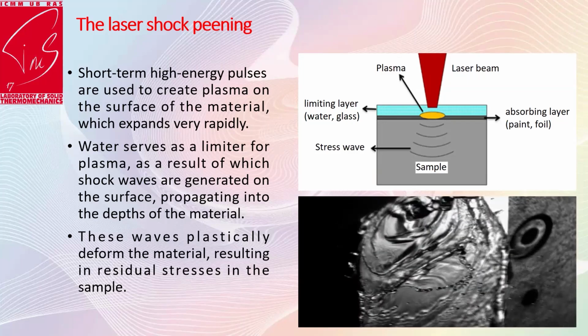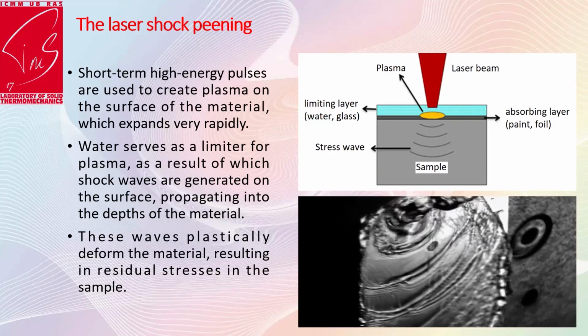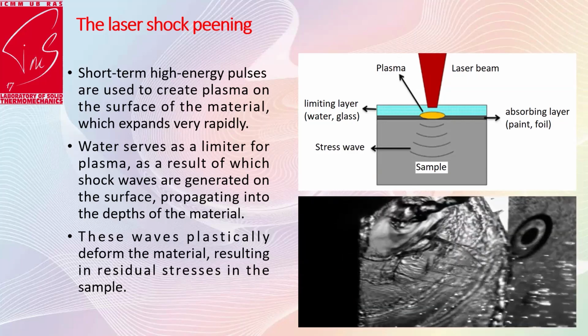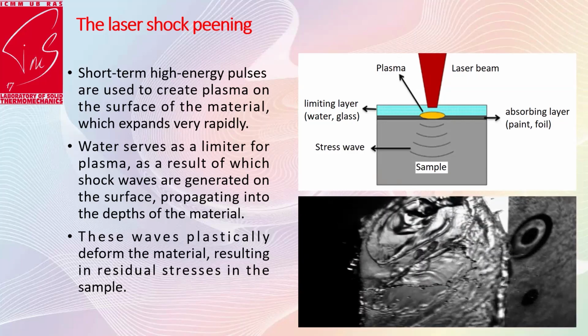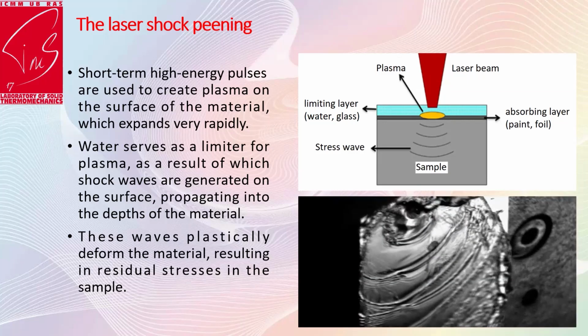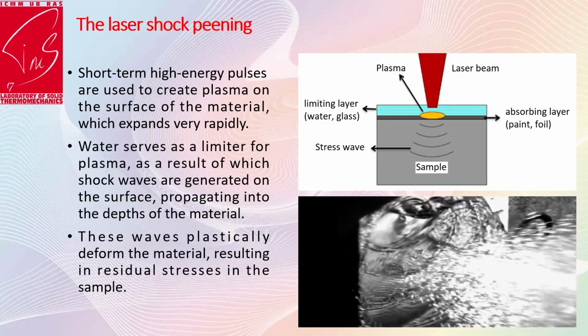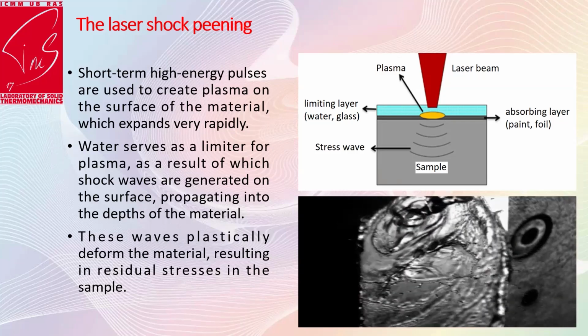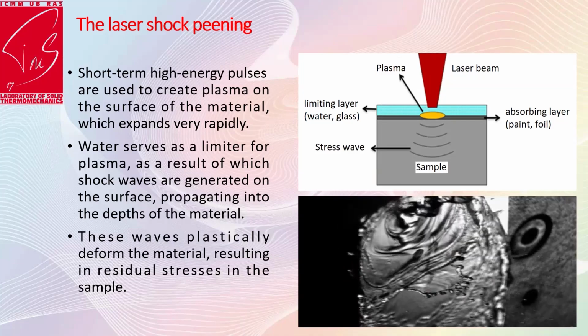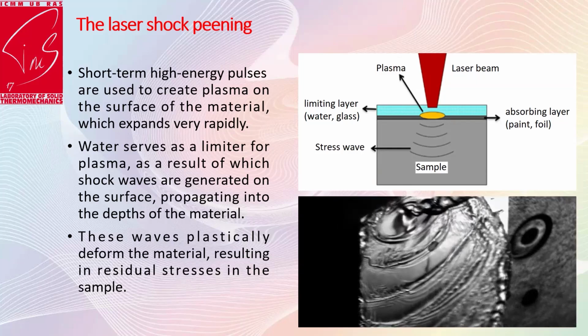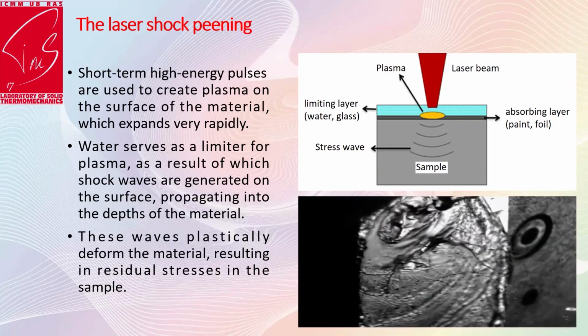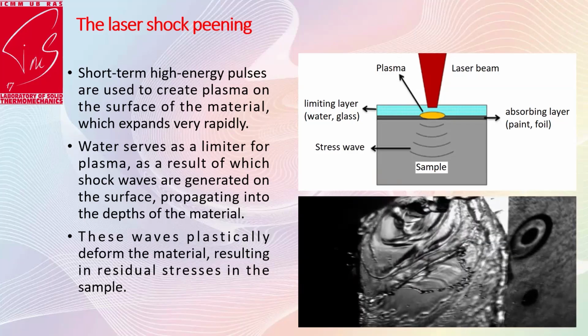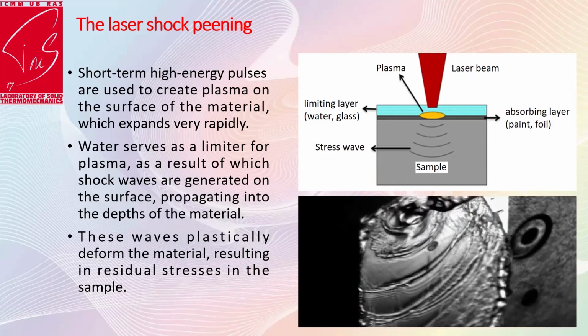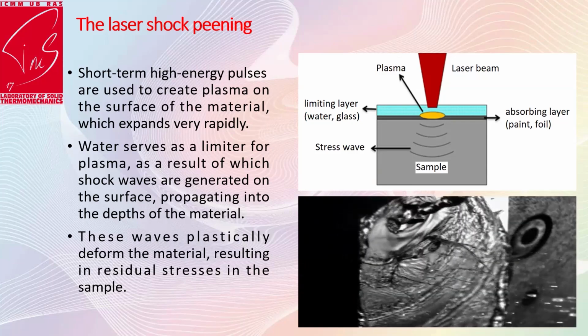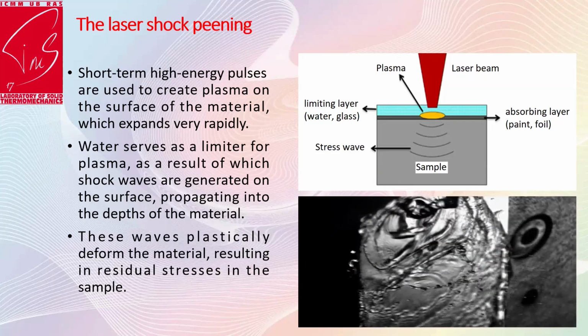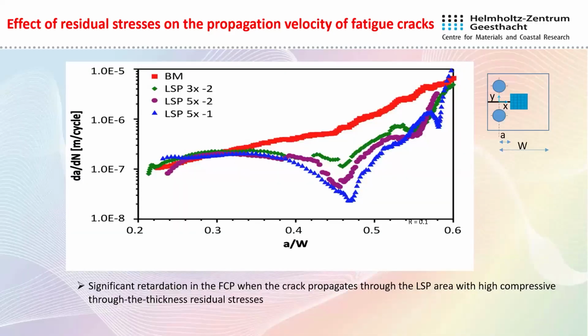The value of this stress is up to -1 gigapascal. So it's an incredibly high residual stress, and practically you can keep all cracks, all initial defects, and finally, as a consequence, you can increase the fatigue life. So you can read the ideas of this technique, and you can see what's going on. We have a water layer and a laser pulse, and after that, plastic deformation. So it's a very funny story.